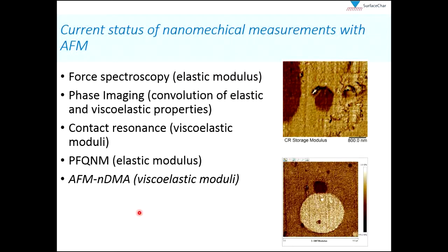So the current status of nanomechanical measurements with AFM affords us quite a few techniques to get at these properties or contrast. Force spectroscopy is a very well-known, widely used method to probe the elastic modulus. We also have phase imaging, which is an imaging method that derives its contrast based on a convolution of elastic and viscoelastic properties. A more recent method that's been developed for viscoelastic moduli is contact resonance.